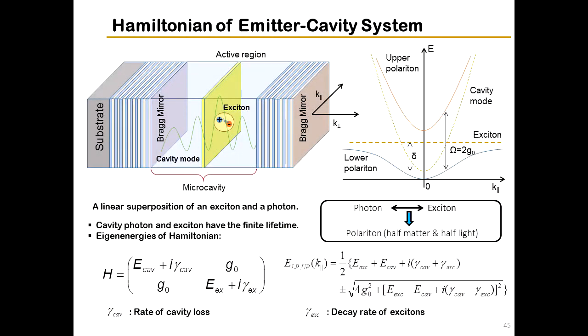So it quickly forms a Bose condensate, which is a coherent condensate, not necessarily in equilibrium, but it can be at a temperature higher than the lattice, but it is phase coherent. And from this coherent condensate, we have spontaneous radiative recombination to give out light. So coherent light comes out by spontaneous emission, and therefore the energy required is much smaller than a normal laser, as you see. So the processes of stimulation and emission are separated here. Whereas in a normal laser, stimulation and emission are one and the same process.